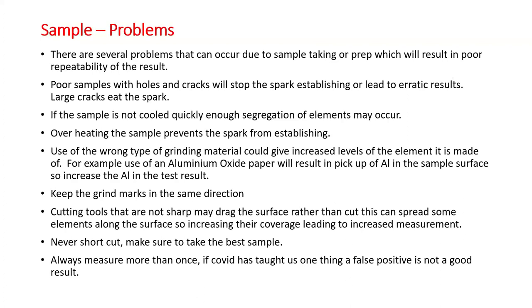Cutting tools that are not sharp may drag the surface. So as you're cutting, rather than a nice clean cut, it's a little bit like spreading butter across the surface. A typical example of this would be copper or leaded copper. As you cut with a poor tool, it actually spreads the lead across the surface of the material. So when you first start to burn, you're going to get high concentrations of lead because that's been spread across the top, and it's actually hiding the true composition of the material.